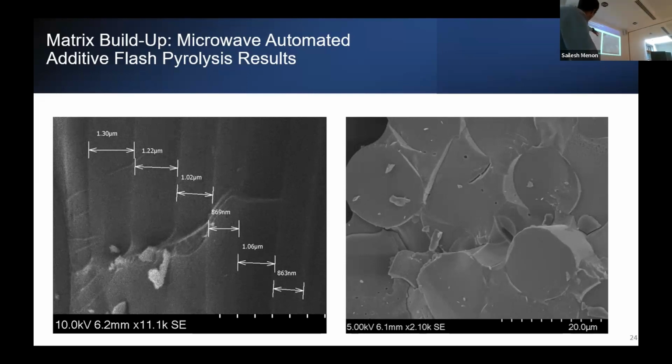Right now we're doing about a micron, but you can do it much thinner. You can go down to 500 nanometers or even less, 200 nanometers per cycle. At that rate, especially with this low contact angle and wicking the polymer into these cavities, we might see a better buildup where the fibers aren't necessarily right next to each other. In a woven composite, when you have your warp and weave going next to each other, there is going to be a distance between those two tows as they're woven together. So when you're looking at a textile-based ceramic preform, it's a question of making sure you get the right thickness, and you can also potentially change the polymer dilution percentage as it's being fabricated.